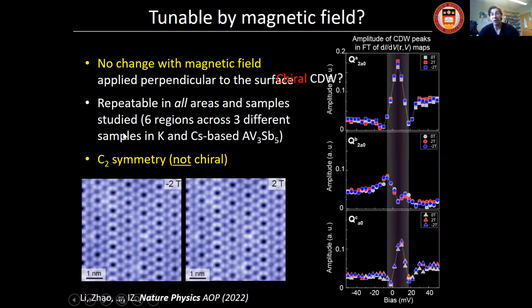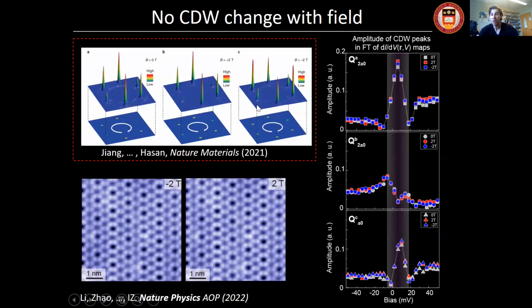It is repeatable in all areas and samples that we studied. We studied 3 different systems across 6 different regions, and the symmetry of this state really seems to be C2 symmetry with this one reflection line. So it's not chiral as was previously proposed, and this is in contrast to the Hasan group, who studied the same material from the same set of sample growers and found that there is a chirality reversal.